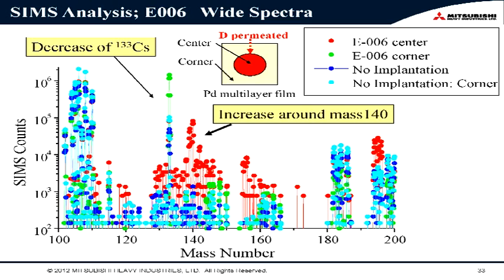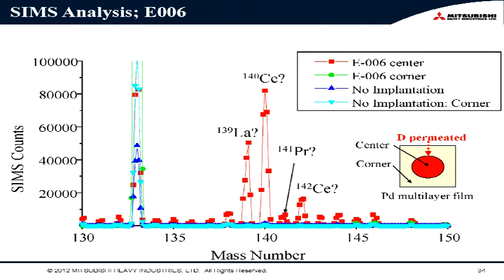But around mass number 140, we can see an increase, the red region, for the permeated area. And this one is an enlarged spectrum along mass number 140. We can see that only in the permeated region we have some mass number 140, 139 and 141, and in the other reference and the corner we cannot see them if we use a linear scale. So we have a large amount of these mass numbers in the permeated region.